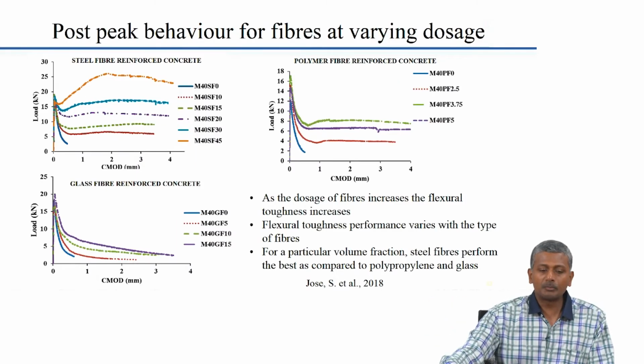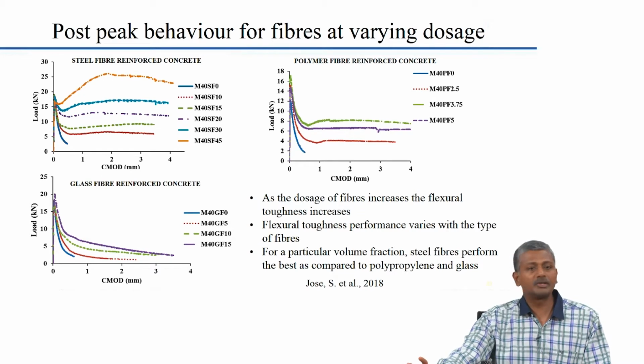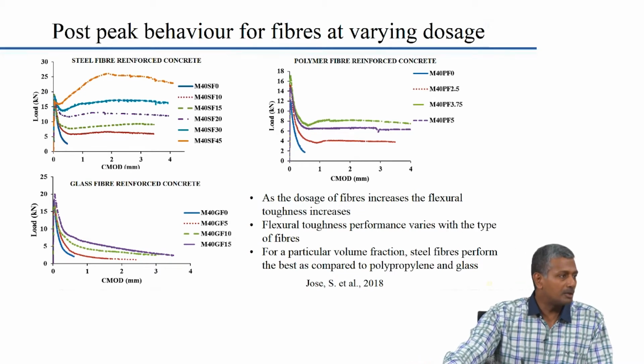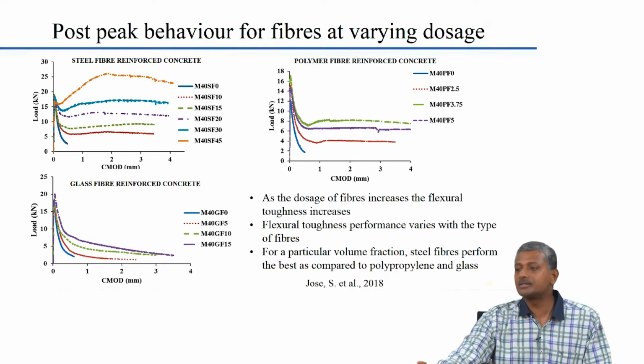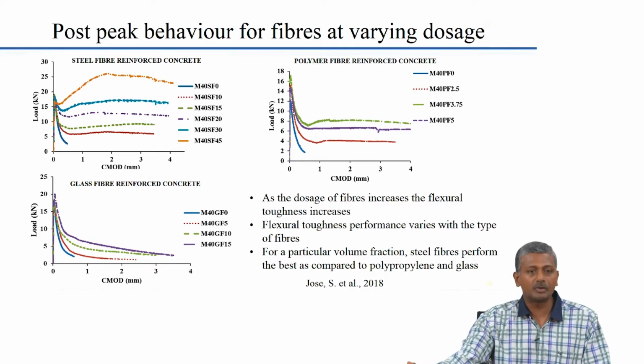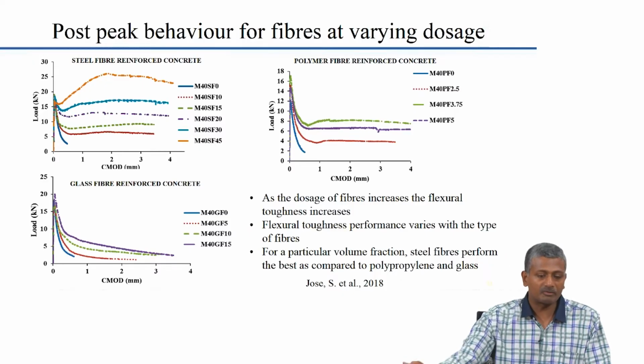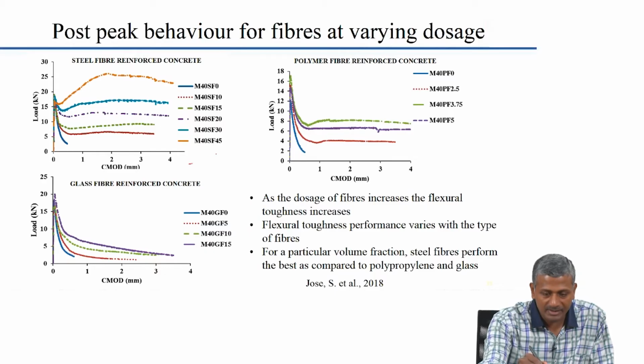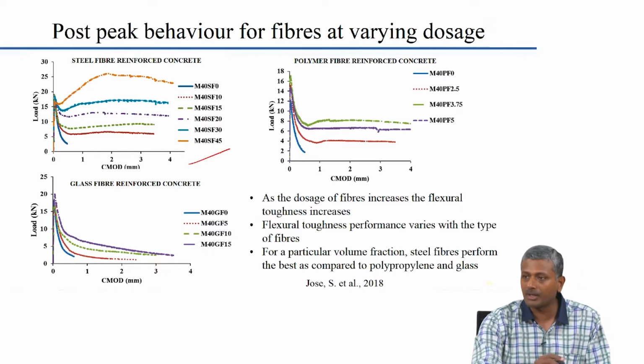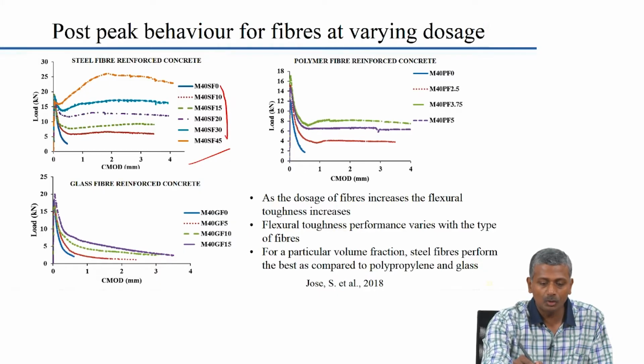Now, of course, the post peak behavior of fibers, as I told you earlier, can vary a lot depending upon the type of dosages that we have. Initially we had talked about the engineered cement composites. When you have a very high fiber loading, you may actually end up getting a strain hardening behavior from the fiber. Indeed, that is what you are actually seeing in this result here. These are M40 concrete mixes with steel fibers at different dosages, starting from 0 all the way up to 45 kilograms per cubic meter.